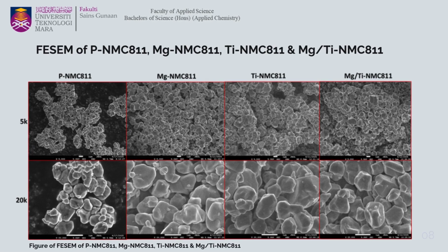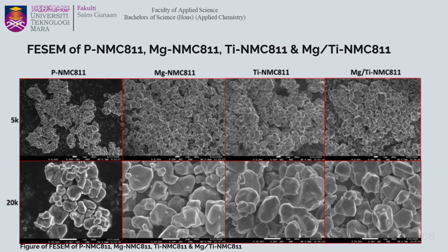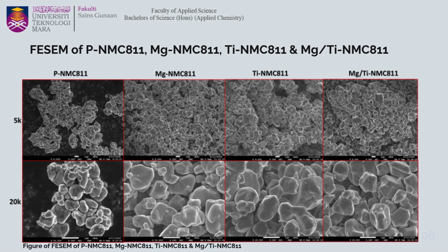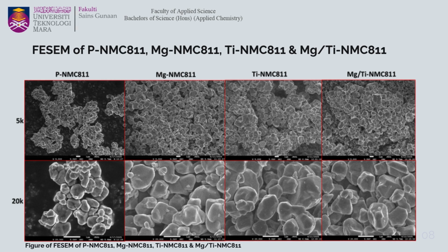Okay, the next slide is the FESEM image of the magnesium-doped NMC sample. As seen, it is less agglomerated, and it shows that the particles stand alone and tend to appear as single crystals compared to titanium and the co-doped NMC. So this improved dispersion may be due to magnesium's ability to control grain growth. So this may enhance surface stability and improve the lithium-ion transport pathway.